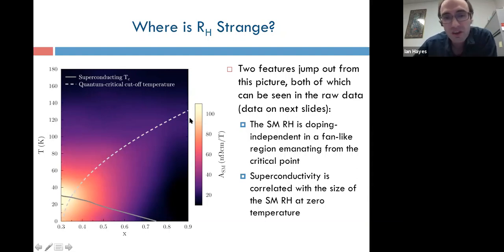So this is striking. There aren't too many experimental observations that actually paint the fan quite this clearly. So this is fairly striking evidence in favor of the idea that this effect is coming from the influence of the nearby ordered phase.